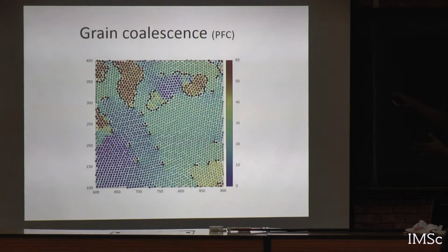Whereas in the Lennard-Jones, as Onuki has also seen, you find a long living metastable polycrystalline state, but if you wait for very, very long, everything becomes a single crystal in the Lennard-Jones case. Even with impurity. So for example, in other cases you find a critical shear.